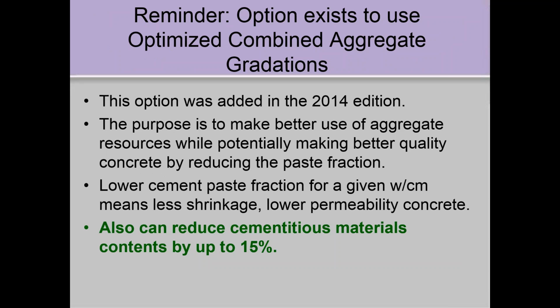Okay. While I'm on aggregates, I just want to remind people that starting in 2014, A23.1 allows combined aggregate gradations, optimized combined aggregate gradations, in addition to the standard picking a fine aggregate and picking a coarse aggregate, often which leaves a gap and doesn't lead to optimum packing. You can actually optimize the whole gradation as a single fraction.